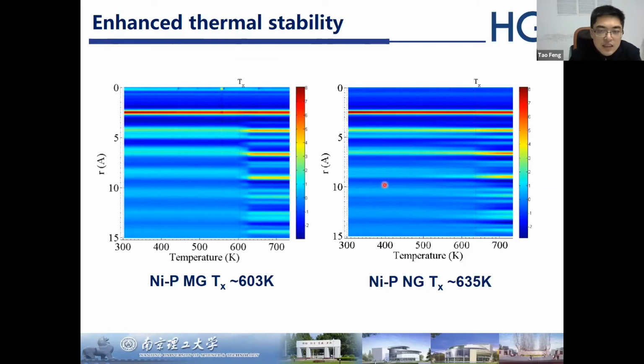First, we will show you that this nanoglass has enhanced thermal stability. This is the in situ X-ray diffraction pattern, and it shows the crystallization temperature of the nanoglass is much higher than the metallic glass with the same chemical composition. And this indicates the nanoglass has higher thermal stability. That indicates that during this atomic rearrangement process upon heating, the nanoglass with more free volume can reach a more stable energy state.